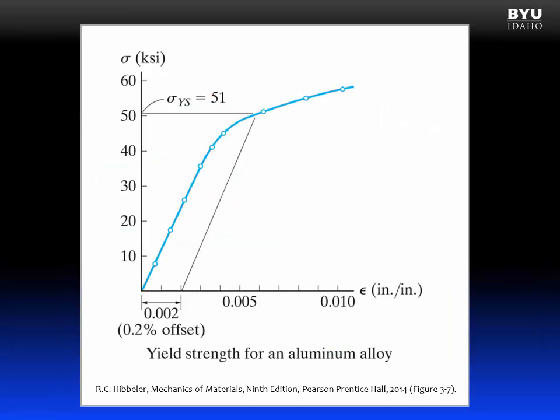Here's a part of a stress-strain diagram for an aluminum alloy. You can see that for this aluminum alloy, there is no yielding phenomenon. And that can make determination of the yield stress or yield strength of the material somewhat difficult to determine. One method that exists is called the 0.2% offset method for determining yield strength. For this method, a strain value of 0.002 is identified on the chart. Then a line is drawn parallel to the initial linear portion of the data. And where that line intersects the data curve for the stress-strain diagram, that point we will identify as the yield stress. This is just one method, and others exist, for finding yield stress in materials that do not experience the yielding phenomenon we saw in mild steel.